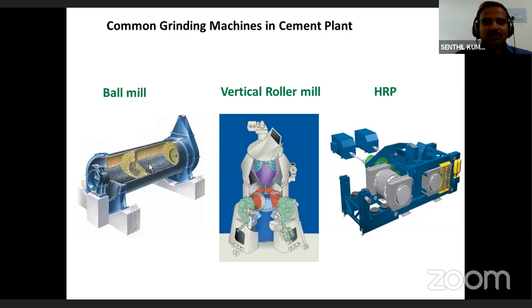That will not happen. So based on the wear rate, what we do is top up the media. We add more grinding media to the system. For example, I measure the wear as 40 grams per ton of material, like raw material or cement. Based on experience and several measurements, I get the value as 40 grams per ton. So I know that after 1 month or 2 or 3 months, the performance will not be the same as a new one. So I know the established value as the wear rate.